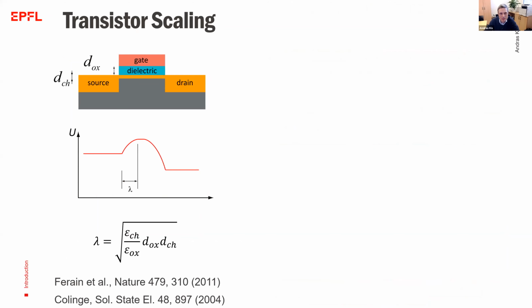They are dissipating energy as we're shrinking them down. So the so-called leakage currents become more and more dramatic. And these leakage currents are coming from the fact that if you make a field effect transistor in this simplified geometry and you try to apply an electric field to switch it off via the gate electrode, then the electrostatic potential, which should prevent the electrons and holes from tunneling between the source and the drain electrode when the transistor is off, becomes less well-defined and more blurred because the sizes of the structure are becoming smaller and smaller.